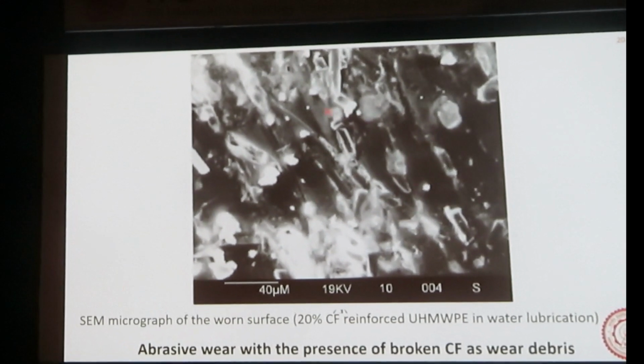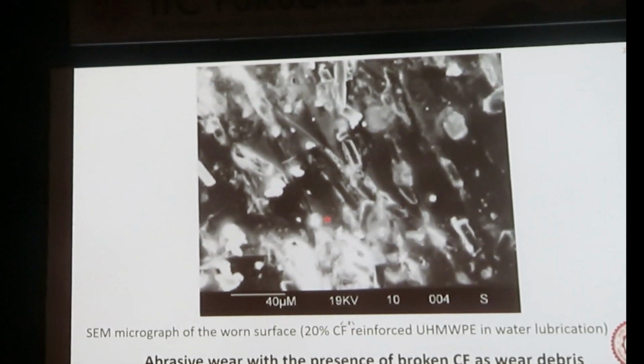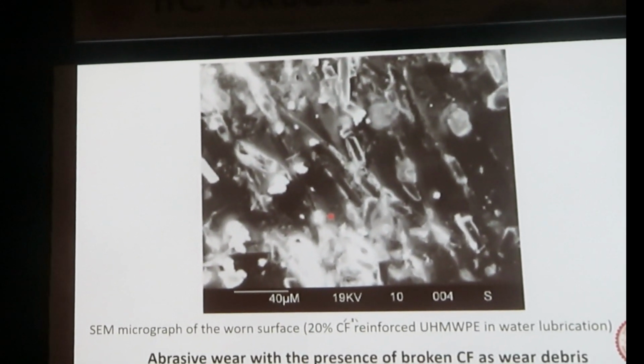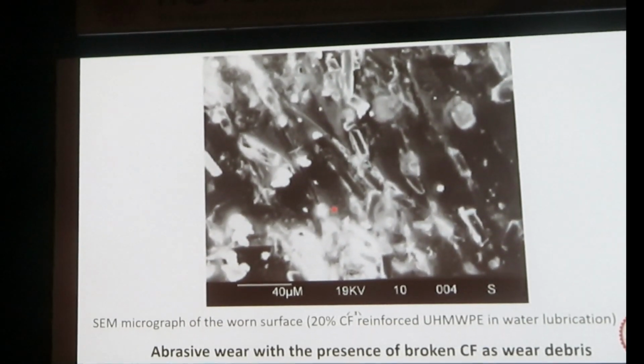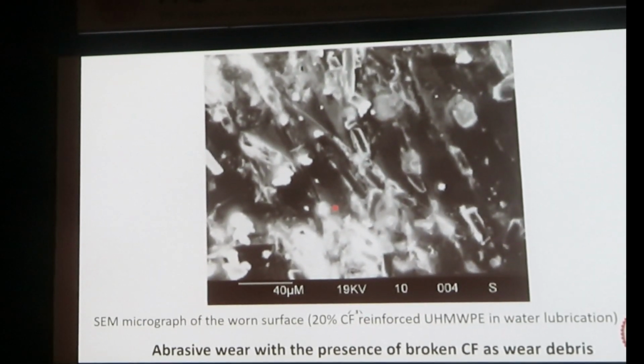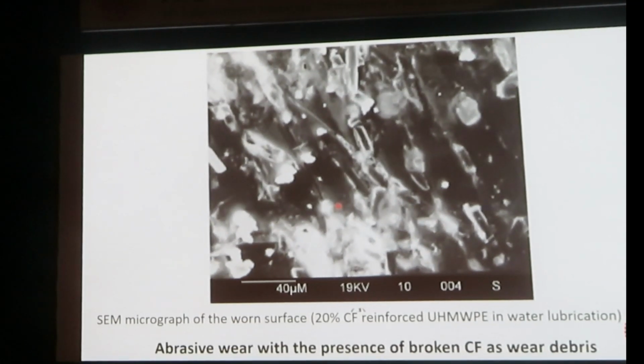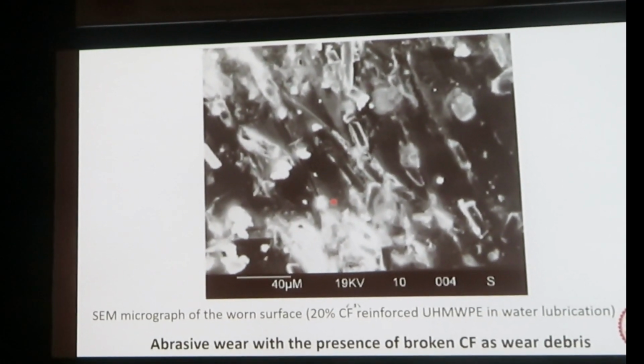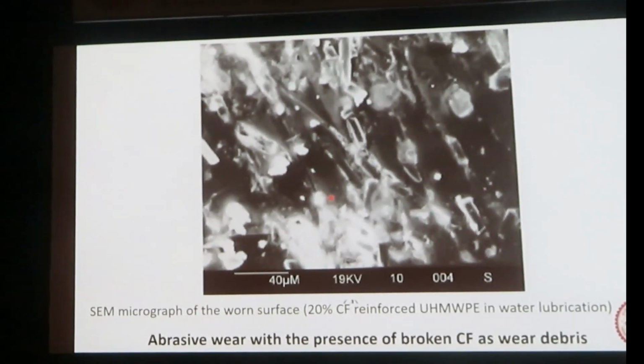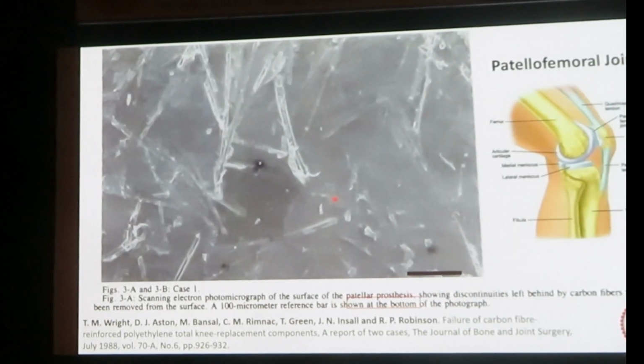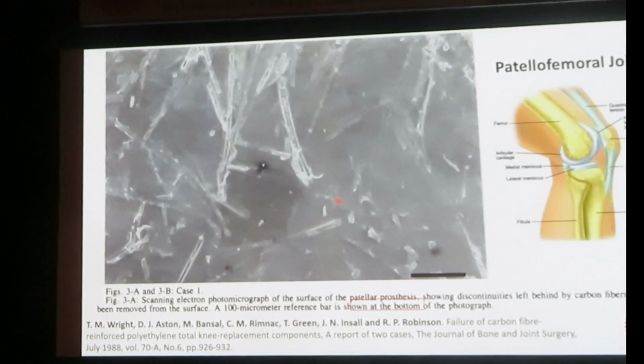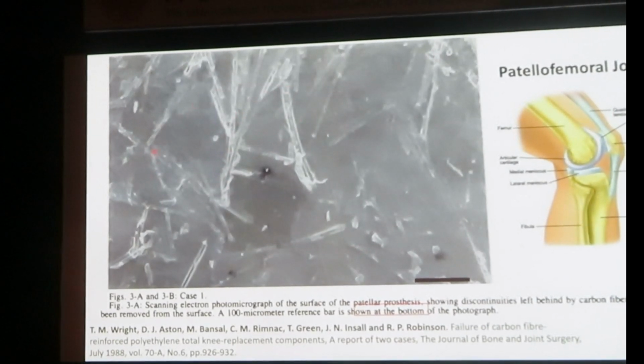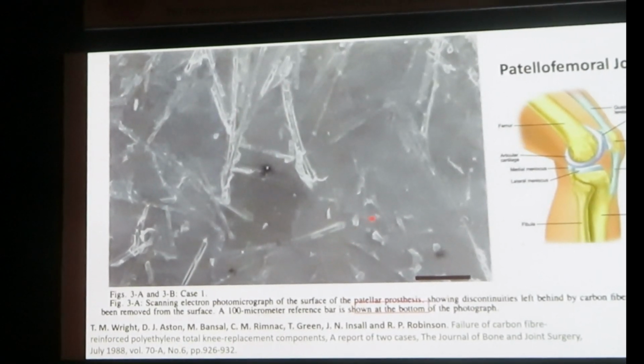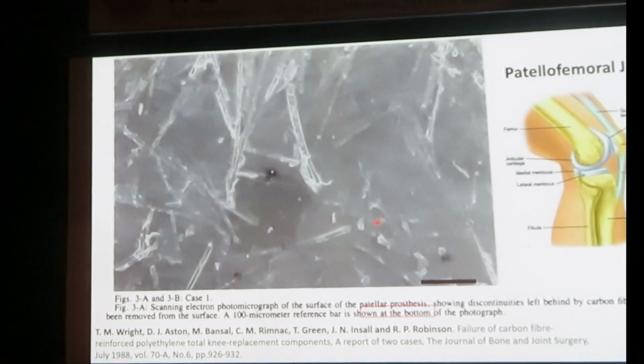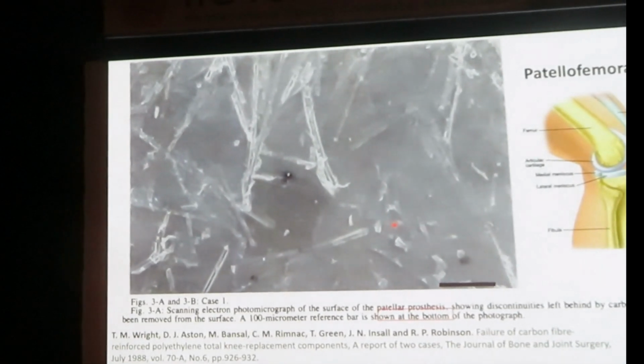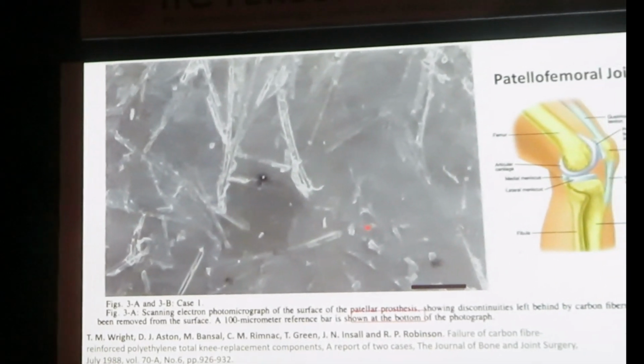Basically, wear failure happens by pull out. Carbon fiber gets pulled out from the surface, and these kinds of pulled out fibers will be very dangerous for the joint. That's why these kinds of composites may not be suitable. Some case studies have been published where the fiber pull out was observed, and these joints were tried in actual patients, and basically they failed.